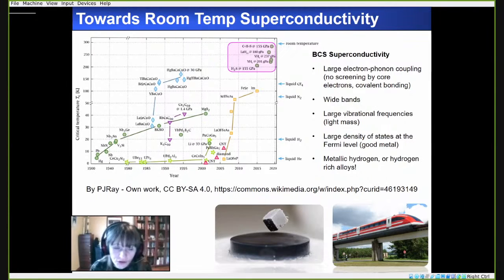Therefore, Neil Ashcroft also proposed much later that if we had hydrogen-rich alloys, the chemistry would be able to pre-compress the hydrogen, and it would be much easier at lower pressures to achieve states that would have similar properties as pure metallic hydrogen, that is the large electron phonon coupling, large vibrational frequencies, and so on. And therefore, we could get room temperature superconductivity potentially at lower pressures than within pure hydrogen.